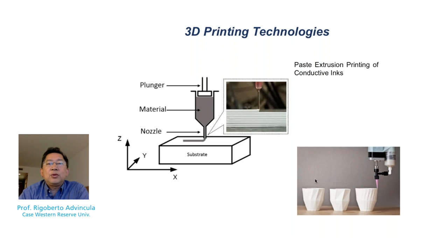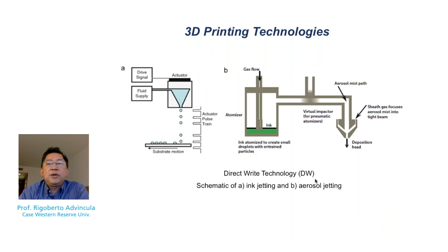Perhaps one of the easiest ways to 3D print conductive paste or inks is basically to formulate your paste or a viscous solution and then force it through a plunger or a syringe with a CNC movement head. And then the thixotropic behavior together with sufficient yield stress, or shear thinning behavior, extrudes the material out, even at room temperature. So in this way, you can actually 3D print at room temperature without the application of heat or even without the application of UV light.